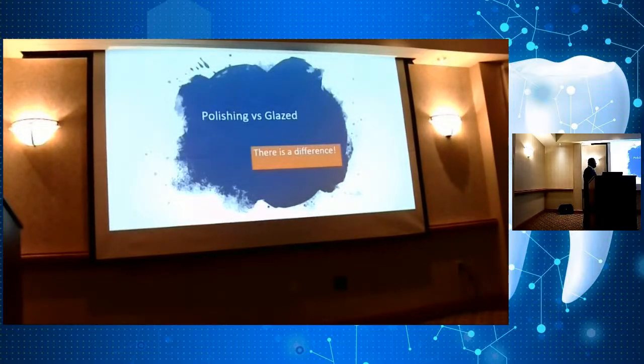Polish versus glaze. We're going to cover this really quickly. Every restoration that I would glaze, I always polish. And here's the reason: because the optical properties change very quickly. Anytime you're sintering a restoration, you have an oxide layer that's formed on there. You want to get rid of that. So when you polish this material, I should say smooth this material, not really polish it, what you're doing is you're actually getting rid of this oxidation layer so light can penetrate right into it.